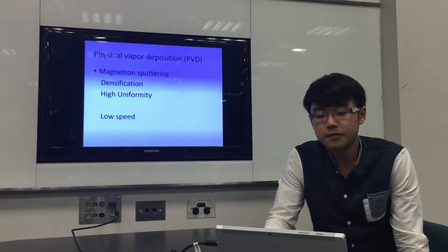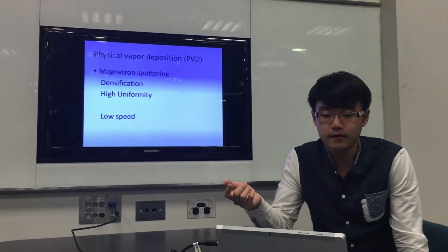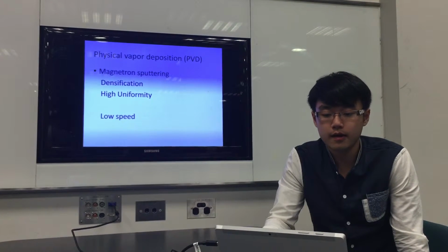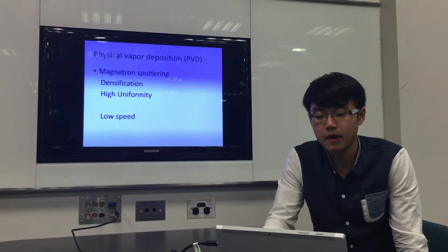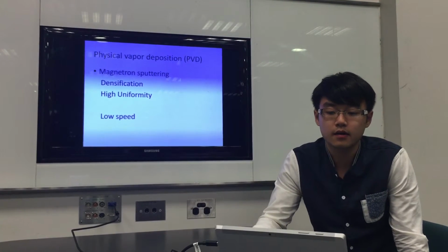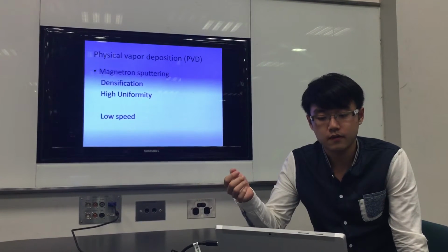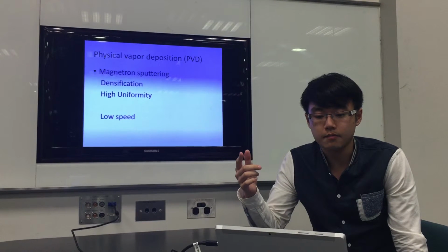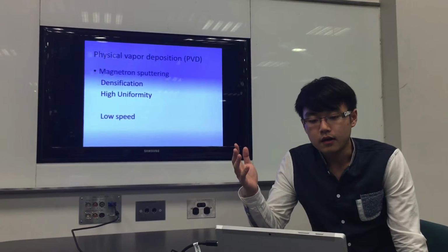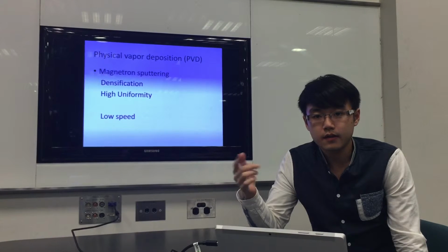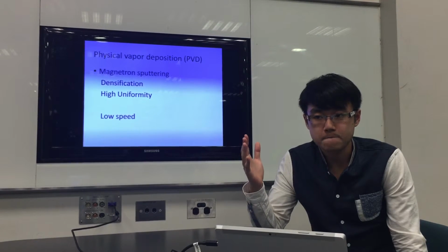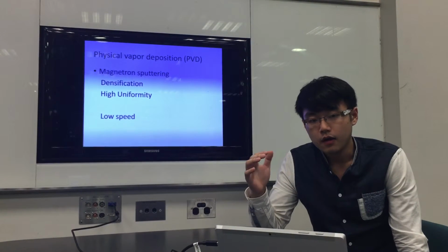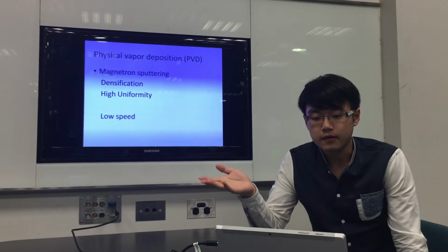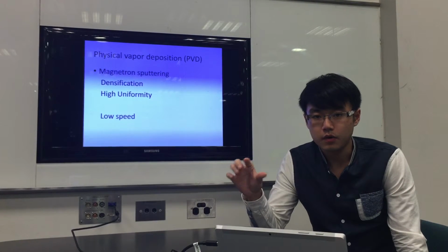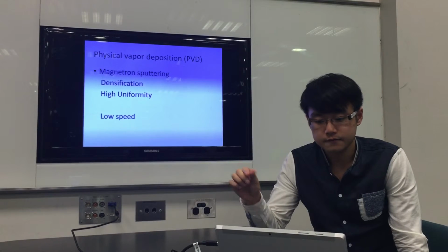In physical vapor deposition, you have another method. We call it magnetron sputtering. In this method, the surface is smooth, and it also has high uniformity. But in this method, the speed is very low, very slow, because if we make the speed up, the coating will not be covered enough.